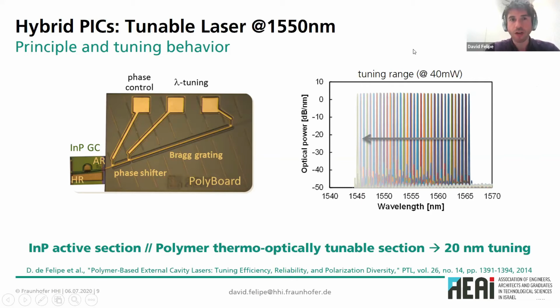So this is a very interesting element that we've been developing in the last 6 to 7 years. And it shows exactly the combination of the two best materials for each function, right? Polymers for the thermo-optical tuning, and for the active part, we need something that is not polymers. We use indium phosphide elements developed by our colleagues, the different groups that developed the indium phosphide components.